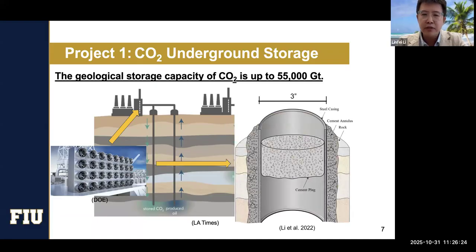But if you take a look at this wellbore system, it has a steel casing in the middle, so it's pretty narrow. The width sometimes can go below 3 inches. And then you have the rock formation. People drill a hole and then put the steel in it. But at the same time, you also have to fill cement in the middle, trying to fill the gaps. Otherwise, the gas or the oil is going to leak, right?